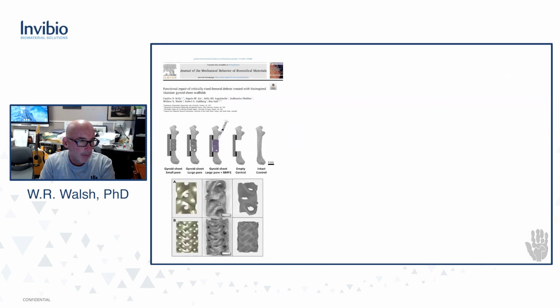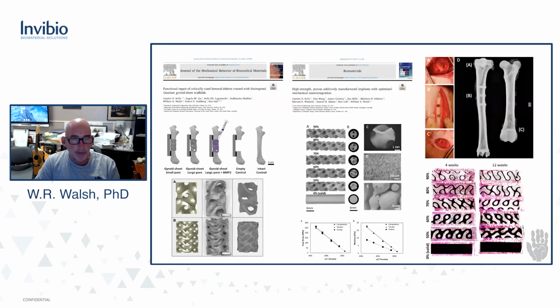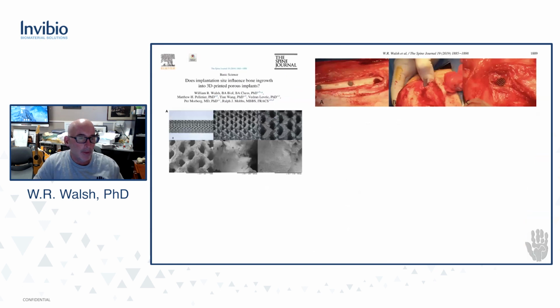A recent paper we did with Cambry Kelly and Ken Gall, now moving to metal additive manufacturing with gyroids and segmental defects, and another paper with Cambry and Ken and my team, where we varied the porosity of a gyroid that was titanium 3D printed, and we looked at the effect of the porosity of the gyroid on fixation, both in cortical and cancellous. There is an optimal porosity for a TPMS type of structure, again with the exact same model, so it's nice to compare them. You can probably even overlay all the graphs that we've ever published with it to make it easy for you. So we can see a lot.